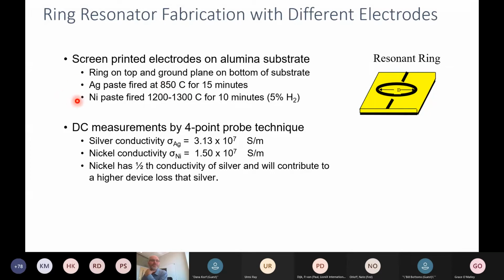So that's why we studied nickel, and it also really was a good instructive set of experiments to show the differences between different metals that we could screen print on a ceramic substrate. So here you can see the nickel conductivity is about half of the silver conductivity. And we made a variety of these rings and tested them.